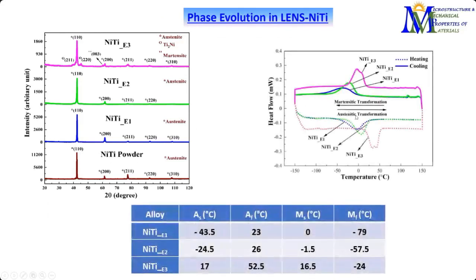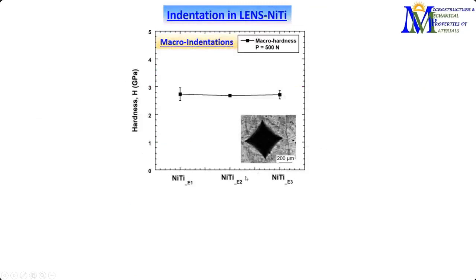This is also reflected in their DSC response, which shows the conversion from austenite to martensite due to temperature change. We've seen that the one prepared with the highest energy density has the austenite finish temperature quite high, even higher than room temperature. So this leads to some variation in the properties.